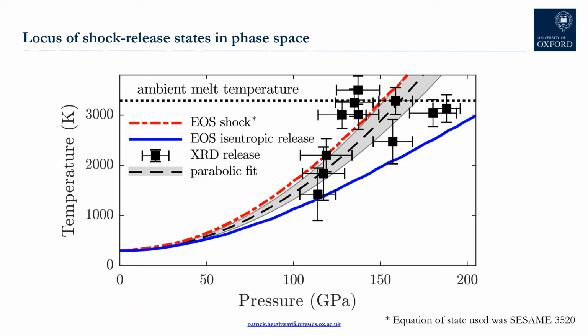This happens because the release path cannot easily cross the melt curve owing to the enthalpy barrier it represents. And so the release path will follow the melt curve back towards its zero pressure value. And this, incidentally, we've also verified using MD simulations. But to conclude, the simulations and the experiments are in agreement and suggest that for these micron scale tantalum targets, shock release is a highly non-isentropic process, contrary to the textbook treatment of the process.